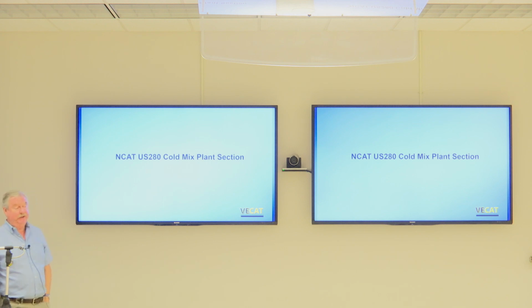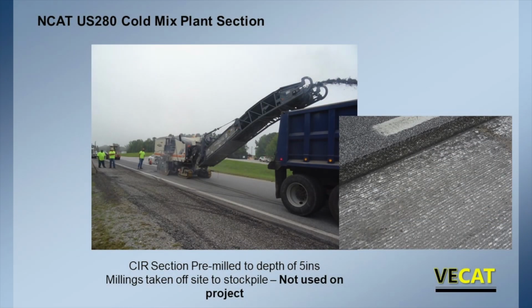NCAT, US 280. NCAT invited us down end of, where are we now, 17? End of 15, to do some test sections for them on US 280. Cold in place recycling with foamed asphalt, cold in place recycling with emulsion, plant mix with emulsion, and plant mix with foamed asphalt. So this was one of the cold mix sections we did for NCAT on a live road, US 280.